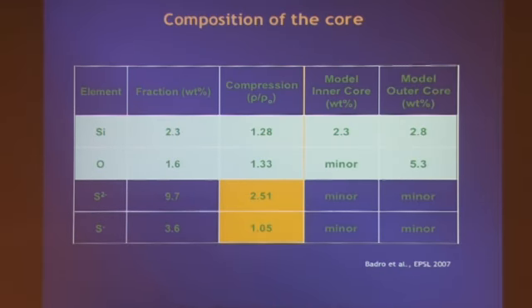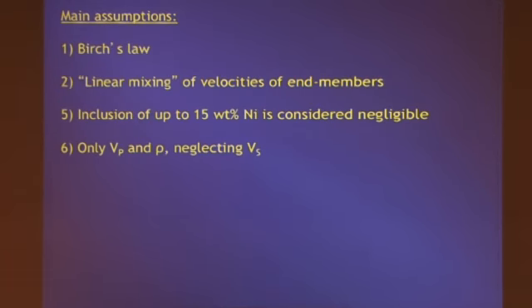But starting from this kind of observation, a model has been put forward, which basically suggests that sulfur is not possible as a main element in the core. And following with the inner core, the combination of these measurements on end member compounds suggests a preferential core composition with about 2% of silicon and a minor trace of oxygen. However, this kind of result has been based on a series of assumptions. The already discussed validity of the Birch law, a linear mixing of velocities of the end member compounds. Furthermore, the inclusion of up to 15 weight% of nickel was considered negligible. And what was, to me, one of the major limitations is that the constraints were coming only from looking at VP and rho, neglecting the third important parameter that we can measure from seismic models, that is VS.